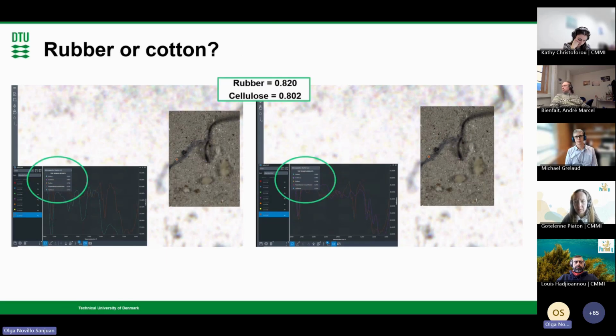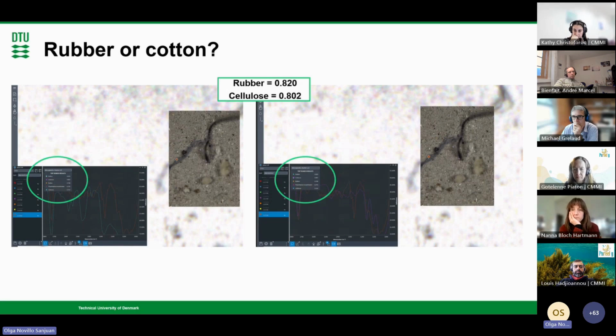Then again, here is another example of mismatching. This was really clear to me that it wasn't a good match, because the biggest match was with rubber, but these samples, I knew where they were coming from, and I knew this fiber. It looks like a textile, and it was a textile, and it is actually cotton. And then you can check with the following biggest matches. So here I showed that the most consistency was with cotton, really, I mean, cellulose. The first, bigger match was rubber, but then I saw that it was cellulose all the time. So here, the good match was really with cellulose and not with rubber. So there is always the risk of misinterpreting the matches also.